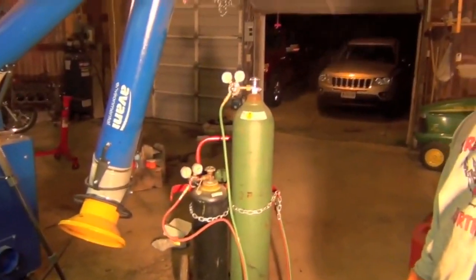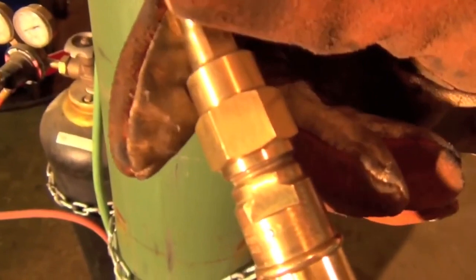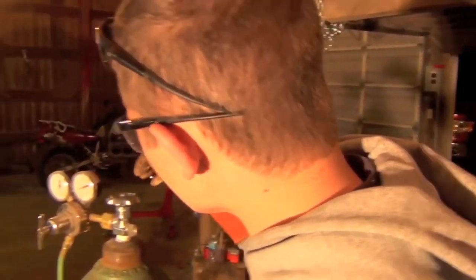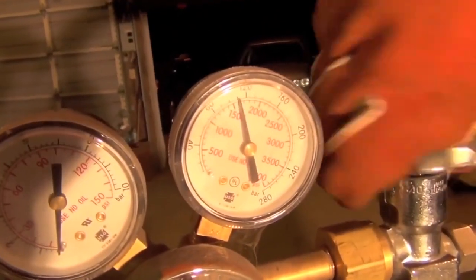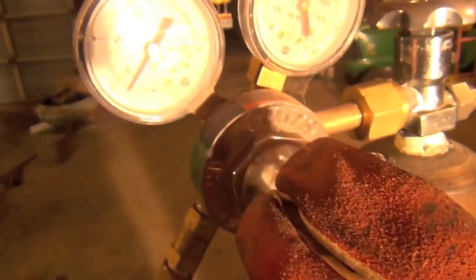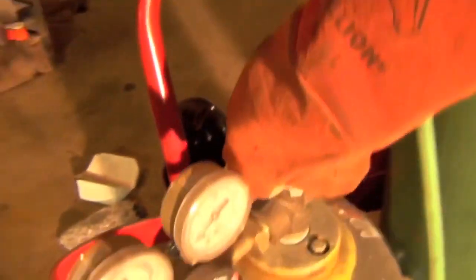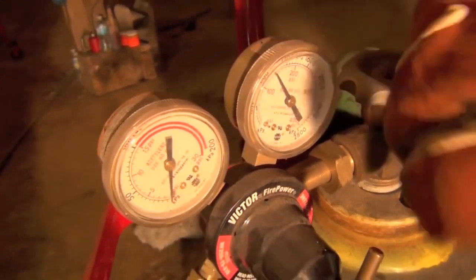Tonight we're going to be using a welding tip on an oxyacetylene rig. We've just got a basic welding tip on here. Most combination torches, you can take the cutting head off and put on one of these tips. Unlike electric welding, we're going to be using gases to get our heat to melt the bronze. If you're familiar with the cutting process with oxyacetylene, you don't need quite as much gas flow. We're not really trying to cut away anything, so we'll just crank this up right in there. We'll try to tune this at the torch. As long as you have enough going to the torch, you can always adjust it there. Right under four psi is normally pretty good. What do you think, no more than like 10-15 on the oxygen side? Yeah, you really don't need much.